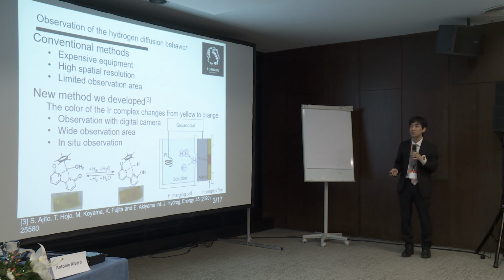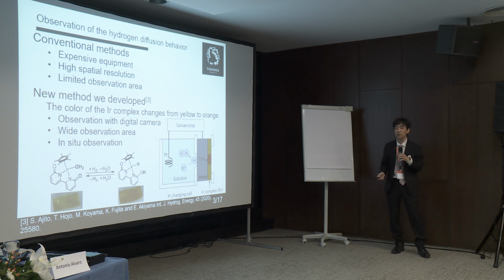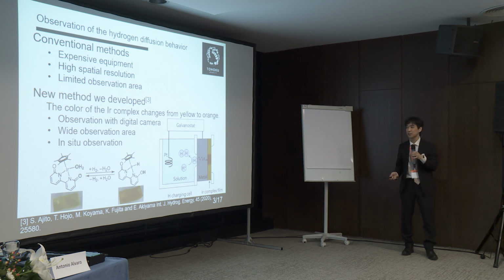In order to overcome this problem, we developed a new method by using an iridium complex. The color of this iridium complex changes from yellow to orange by the reaction with hydrogen. So we can observe the hydrogen by the color of the iridium complex with a digital camera, over a wide observation area and in situ. If we can apply this technique for a stretch-formed specimen, we can investigate the effect of stress and strain on the hydrogen diffusion behavior.